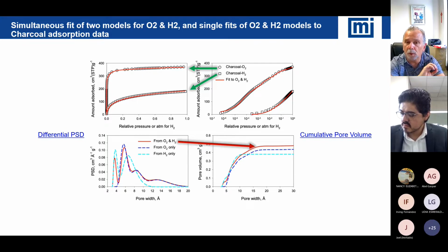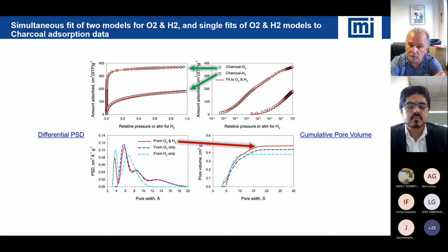component you could put in that will scan your entire isotherm and calculate the appropriate BET surface area. It coincides really well with the article from David at Cambridge. So if you have our software and any isotherm data, you can use it, and it will calculate the correct surface area to agree with what's being published. It is more challenging. I would use nitrogen.